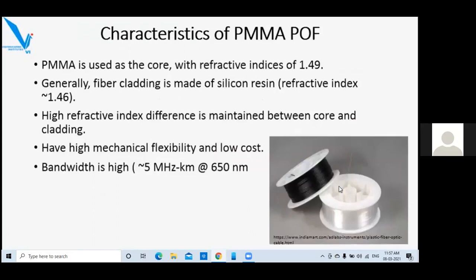Polymethyl methacrylate is used as a core with refractive index 1.49. Generally, the fiber cladding is made up of silicone resin, which has a slightly lower refractive index, that is 1.46. High refractive index difference is maintained between core and cladding. These PMMA polymer optical fibers have high mechanical flexibility and low cost, and bandwidth is about 5 megahertz kilometer at about 650 nanometer.